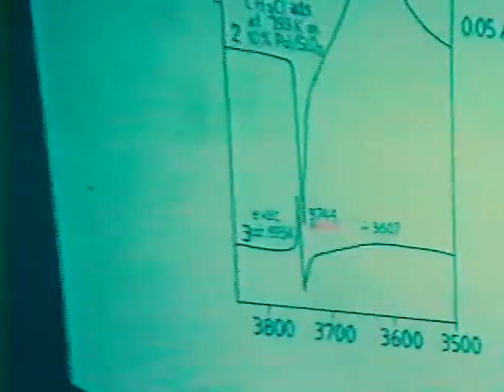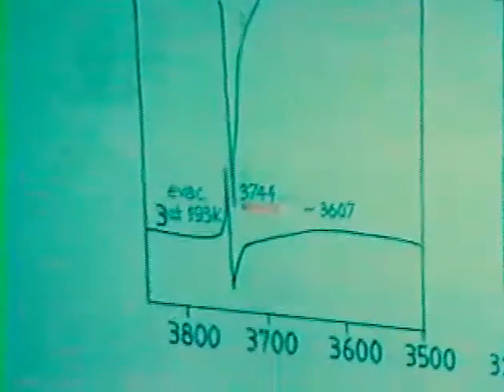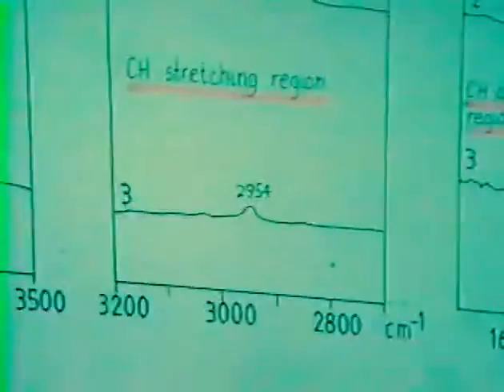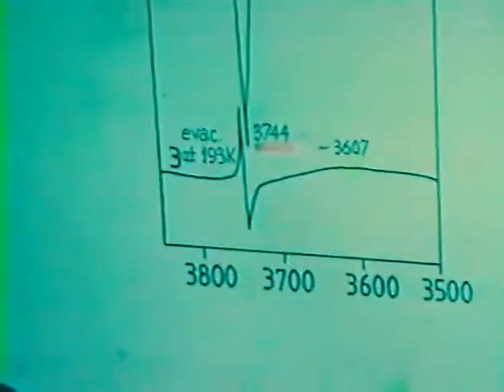More dramatic change occurred in the OH region of the sample. I will turn to this region in a minute. When the gas phase was removed at the same temperature, I mean at the temperature of the adsorption, a very small band at 2954 wave number remained on the spectra, and this big broad absorption in the OH region has been removed. I will deal with this in a few minutes too. Okay.